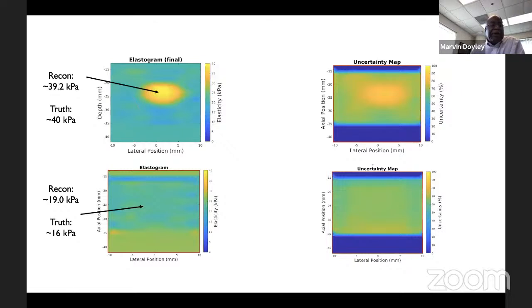If we compare what we measured to what we have, you can see there's good accuracy between these two. And the reason why the error is much, much lower than what we had before is that with the robot, we can do very, very small compressions. The smaller the compression, the more you can get away without really needing two components. When Mike was doing this, I think the compression was on the order of 0.1% between any two images. As you increase the compression, then you really need both components to do a good job.